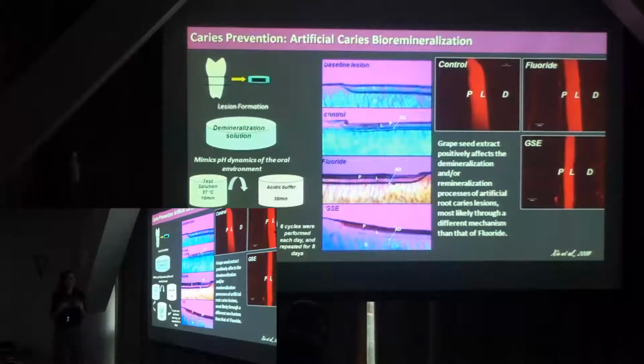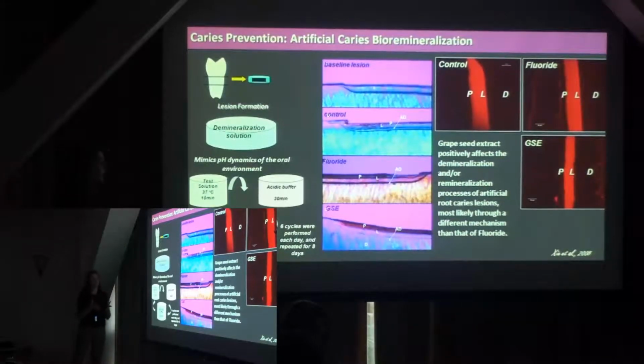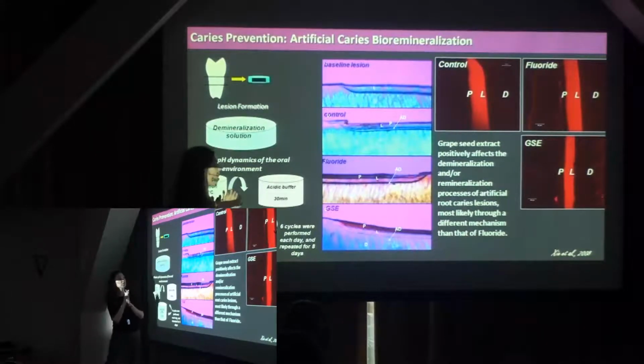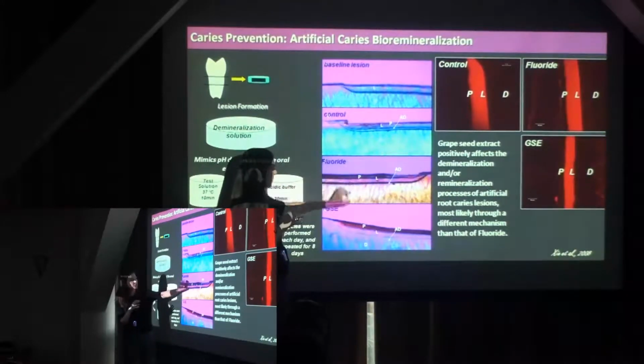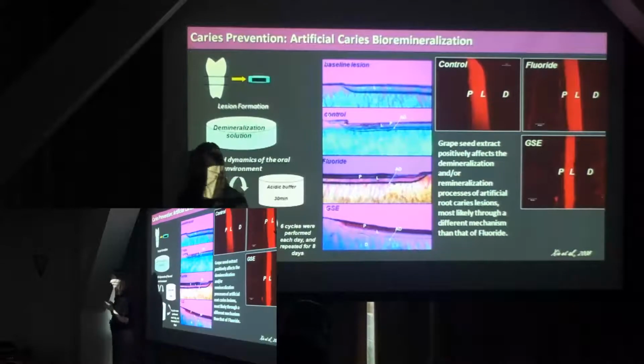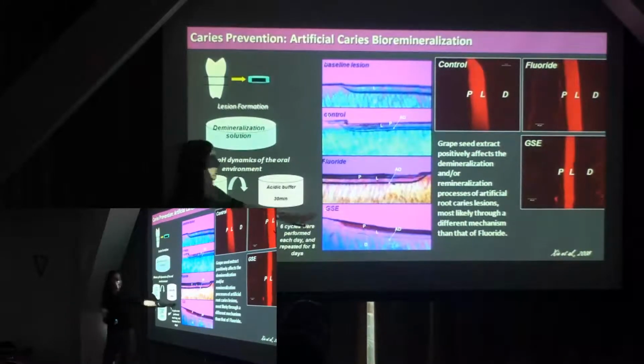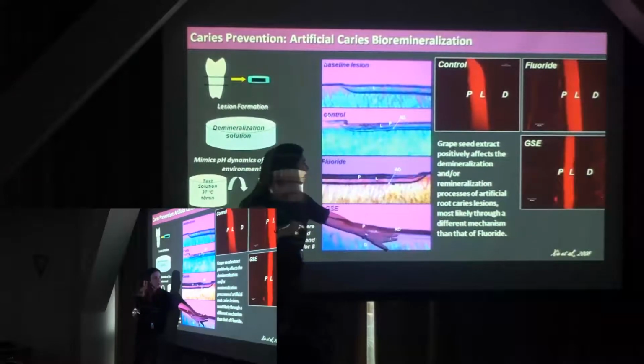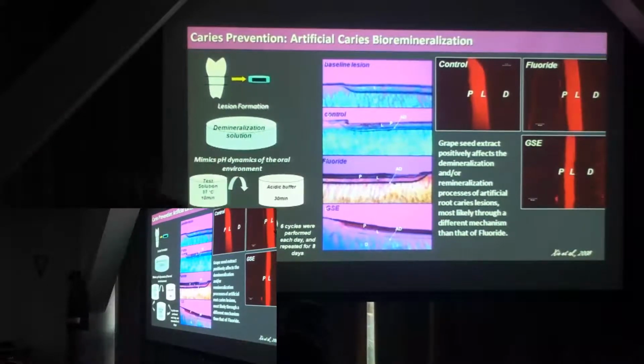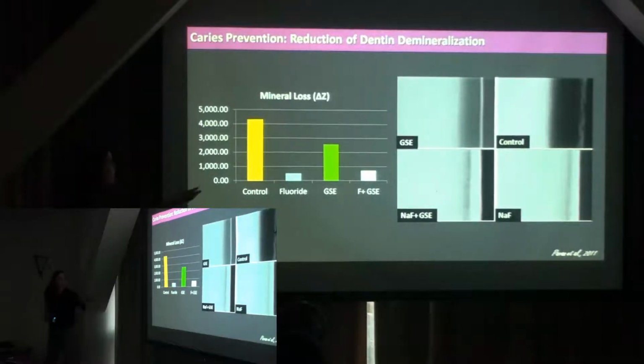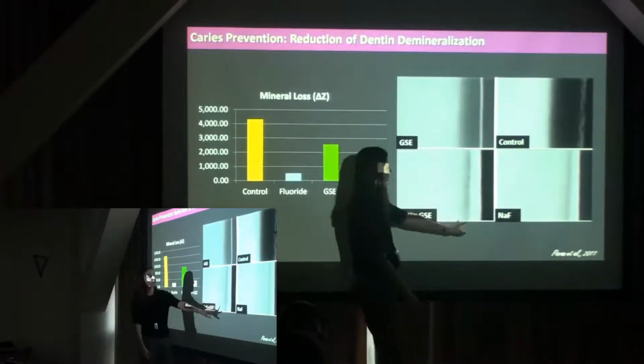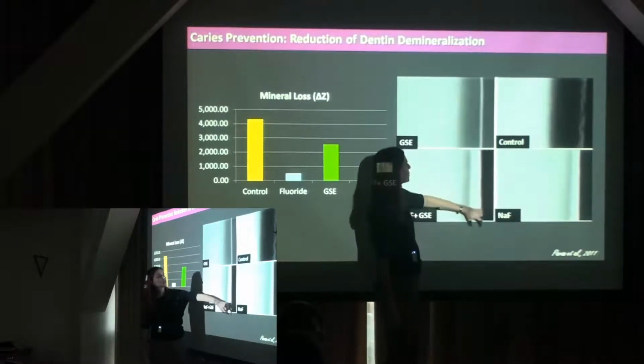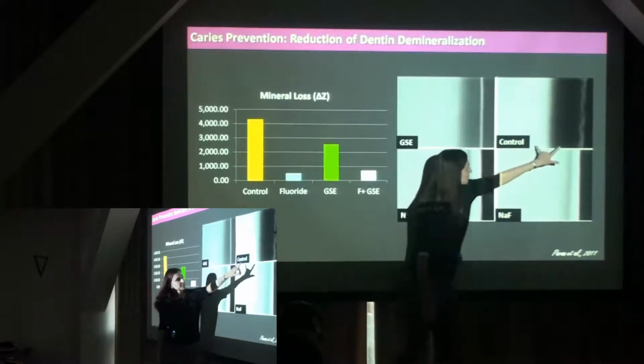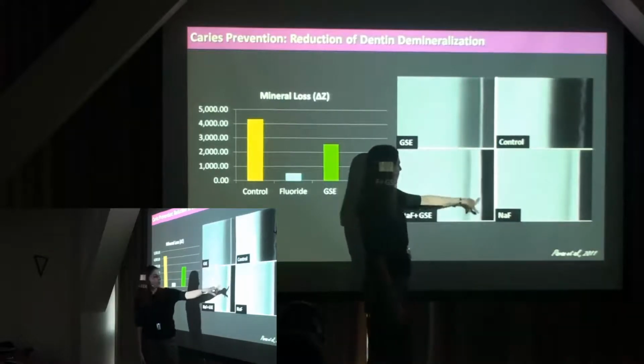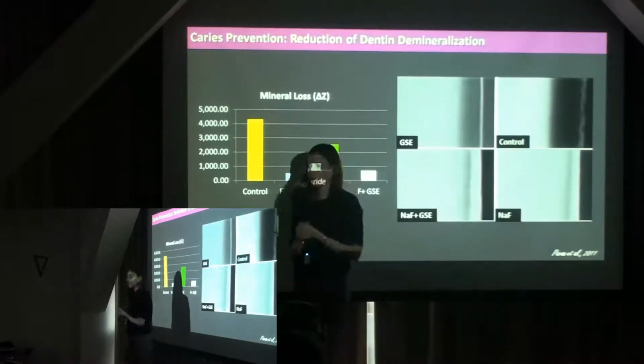So what we've seen is that once we introduce the grapeseed extract, it really improves the remineralization potential. These lesions start getting smaller, all right? So this is the control, this is fluoride. It's behaving very much like fluoride, but with a different mechanism. It actually makes this surface a lot harder than what you would get with fluoride. And this is just another, probably easier, way to see some of this mineralization process. So this is a highly mineralized surface. This is the lesion. This is your control. This is grapeseed, grapeseed associated with fluoride, and fluoride by itself.